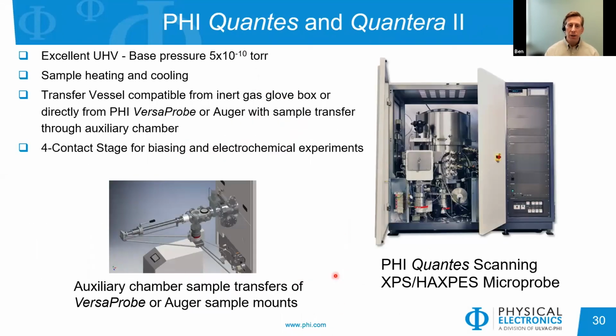For our Quantes and Quantera system, the Quantes being our hard X-ray and soft X-ray system, we do have excellent base pressure, again, because these materials tend to be very reactive to atmospheric gases. It's good to have a good base pressure on the system to minimize those changes during your analysis. We can also heat and cool the samples in the vacuum chamber. And we do have the ability to transfer a sample from, say, the VersaProbe to a special auxiliary port on the Quantes or Quantera, and then analyze it using that system. We also have a special stage and holder where we can bias the sample in situ to perform polarization type studies.